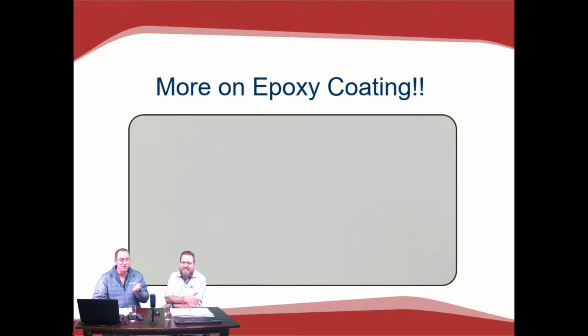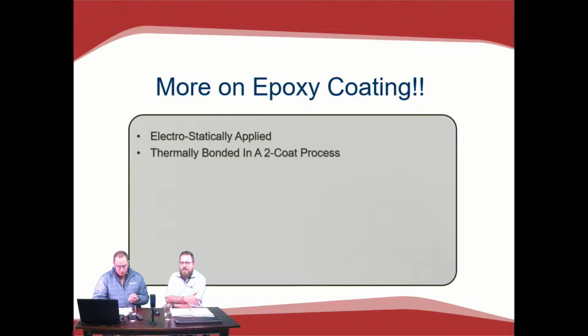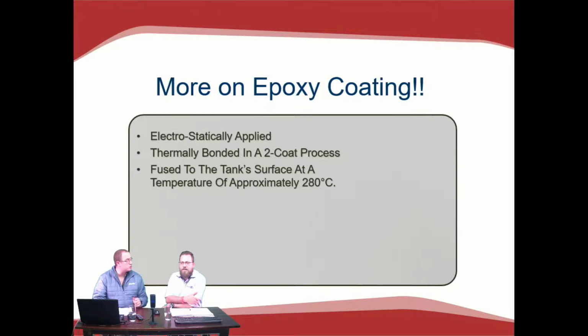So more on epoxy coating. I found that to know more about epoxy coating is very important, so I've got a lot of information about it. The epoxy coating provides a highly resistant coating to the Rhino Tank panels. And the epoxy coating is electrostatically applied and thermally bonded in a two-coat process to the steel panels. This is a dry powder coating that is then fused to the tank surface at temperatures of approximately 280 degrees Celsius. I told you, it's extremely hot.